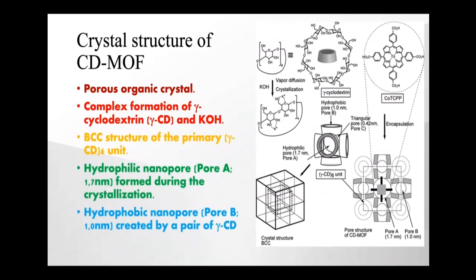Cyclodextrin-based metal organic framework, CDMOF, is a porous organic crystal. CDMOF is prepared by the complex formation of gamma cyclodextrin, gamma-CD, and potassium hydroxide. The CDMOF crystal consists of the body-centered cubic structure of the primary gamma-CD6 unit.